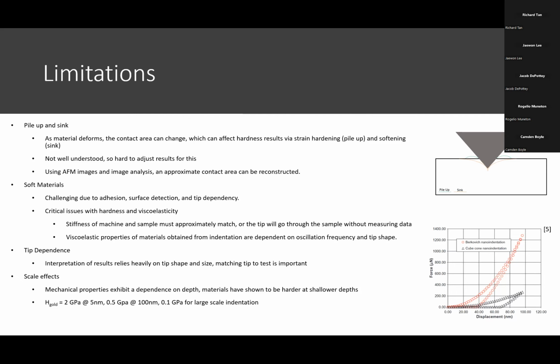The third limitation is tip dependence. I've talked about tip dependence a couple of times now, but the interpretation of your results relies heavily on the tip shape and size. Things like your contact height and contact area all rely on that. Additionally, when doing different tests, matching the tip to the test is important - each tip has a purpose, as stated in an earlier slide. Using different tips for different tests may not be optimal, and this is shown in the bottom right figure: you have two different tips, the Berkovich and cube corner, used in the same indentation, and you get different results. Keep that in mind when planning your tests.